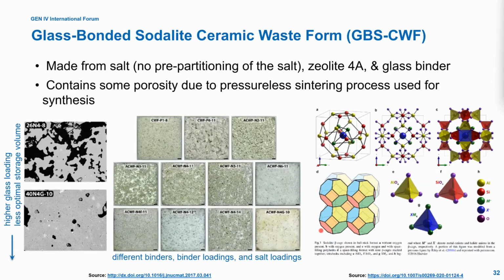When we think about sodalite, the specific sodalite we're working with here is an aluminosilicate sodalite. This is a beta cage that's formed by the aluminosilicate network. Inside the beta cage, you've got the halide alkali tetrahedron that is represented here, immobilized inside the beta cage. That means for every 4 alkali, you can have 1 halide. So you've got stoichiometric limitations on what you can actually immobilize in the sodalite, where almost the entire sodalite is non-waste. It's all aluminosilicate. So the amount of waste you can immobilize in a specific amount of sodalite is not very high.